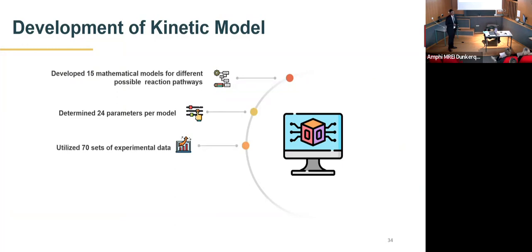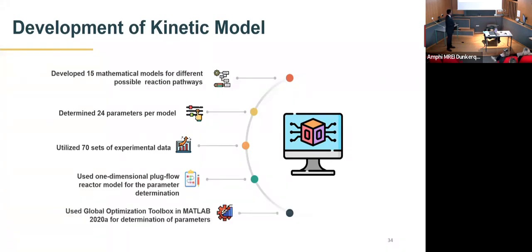We used 70 sets of experimental data, which was obtained by changing the reactant gas composition each time, and then getting the catalytic activity under different reaction conditions. So we gathered 70 sets of experimental data, which we used for the parameter determination for our case. For the reactor model, I used a one-dimensional plug flow reactor model in order to simplify the reaction model development and the parameter determination, obviously. And finally, I used the global optimization toolbox, which is generally available in the MATLAB software, in order to determine the model parameters we have in our kinetic models.